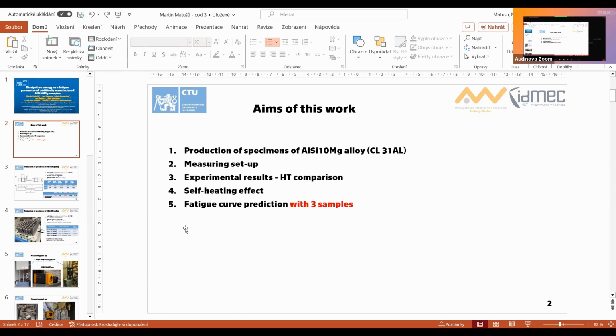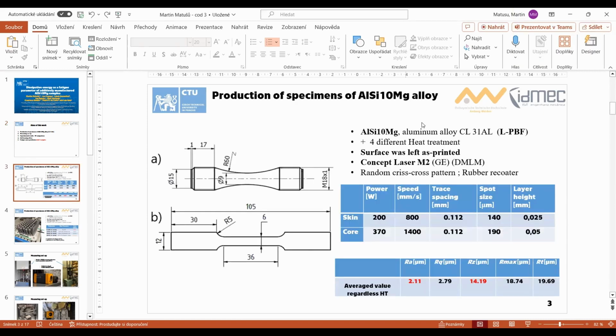Go ahead. Okay, so these are the aims of this work, and here are the specimens which I was talking about. The fatigue life specimen, which has the radius of transition curve into the diameter of 9 millimeters. And the tensile specimen, which you can see on the lower part on the left side. These specimens were left as printed, but heat treated.